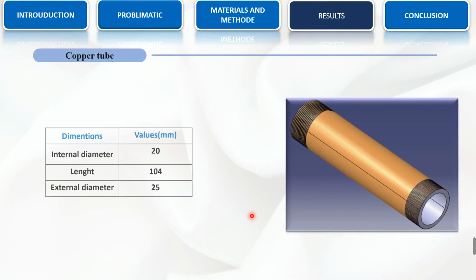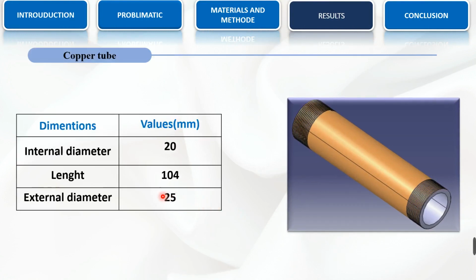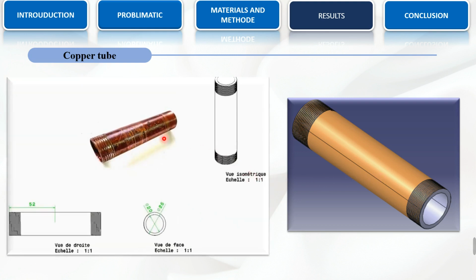We are seeing now the copper tube, which is fabricated of copper material, which has a high thermal conductivity reaching 386 watts per meter Kelvin, 104 millimeters as a length, and 25 and 20 millimeters of external and internal diameter respectively, to assure the fusion of the material inside by increasing its temperature thanks to heaters fixed on the lateral surface of the tube.